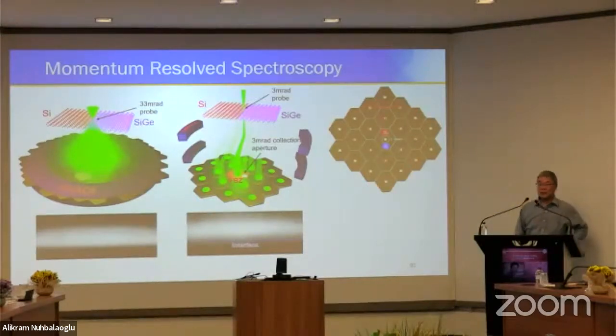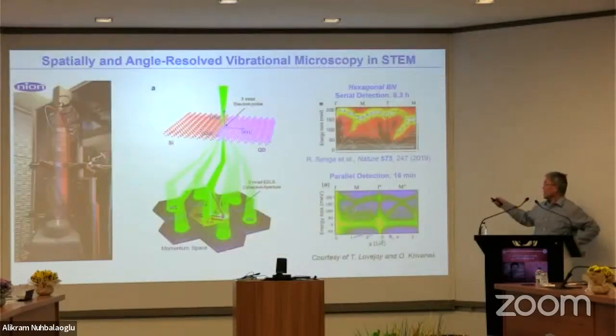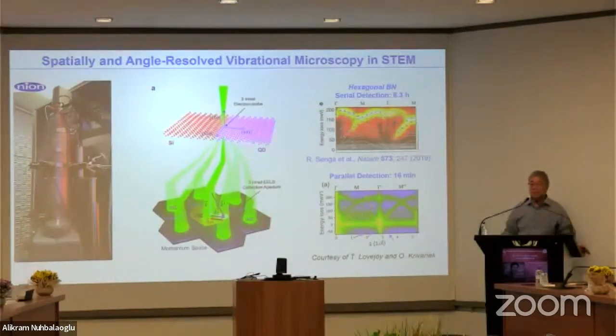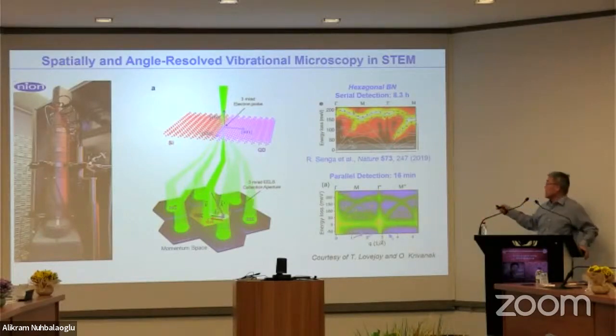In other words, you can measure the phonon dispersion curve from a local region. Okay, so this is just the drawing of the Brillouin zone. There's a first Brillouin zone, and then you have the other Brillouin zones. But most important, if you have a large angle resolution, you can make many data points, and then do the phonon dispersion analysis. So this is an example showing the work Senga and his colleagues did a few years ago. This is the spectrum collected using a huge amount of time. Each spectrum takes about 10 to 20 milliseconds, and these are millions of spectra put together, and it takes very long. But this demonstrated the principle.